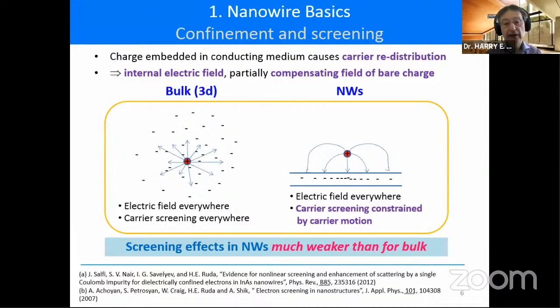In a nanowire, if we're talking about a thin nanowire, where we're now in quasi-one-dimensional transport, because we've got confinement in the radial directions, then it means that to look for a carrier, the carrier can only come from the longitudinal direction of the wire. And so we have to go a long way to find a sufficient number of charges to screen off the test charge, which means that screening lengths are very long, or screening is very poor compared to the bulk. And that, in the sensing section I'm going to show you, is a key to getting very, very sensitive sensors.